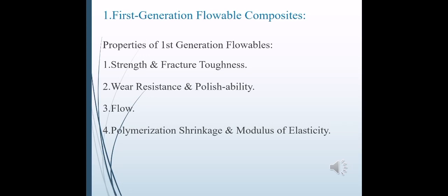Properties of first generation flowables regarding strength and fracture toughness: the mechanical properties were about 60 to 90% of the conventional composites, so they should be used with caution in high stress bearing areas. Their low filler content made them highly polishable, but reduced their wear resistance. The fluidity varied from product to product, and the polymerization shrinkage rate was about 5%.